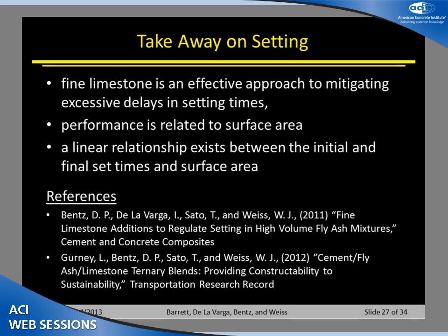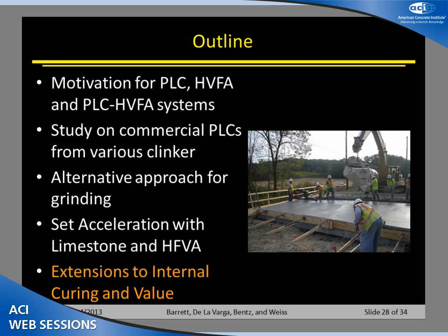And then you can essentially develop a linear relationship between the particle surface area, the particle size, and the set time. And there's a couple different approaches that have looked at this. The final thing that we want to talk about here is really an approach that we're looking at to try to extend the use of high volume fly ash by combining it with internal curing.